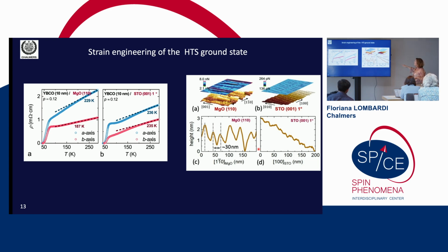So, and this is the morphology of the films. This is an AFM picture. If you take a cross section, you get these triangular shapes of the substrate, and surprisingly, the periodicity of these facets that are unidirectional is very close to what one gets for the Moiré materials. So this is the surface for the MgO that has been reconstructed, and this is the surface for STO that is vicinal cut to get the untwinned films, and you get this step-like picture.